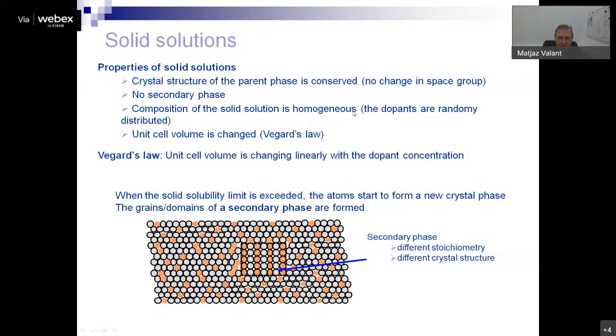It means that the dopants in the solid solution should be randomly distributed, not grouped or clustered in one part of the system and depleted in another part. As a consequence of all this, what we see really efficiently in an XRD pattern, for instance, is that the unit cell volume is changed. And in the majority of cases, the unit cell volume changes linearly with the concentration of the dopant, which we call Vegard's law.